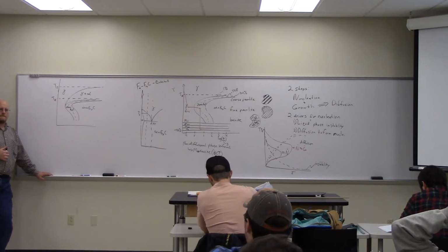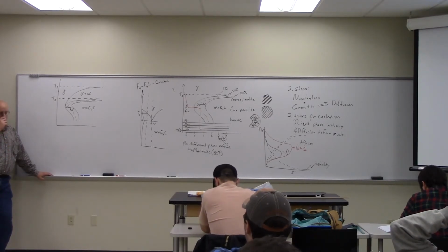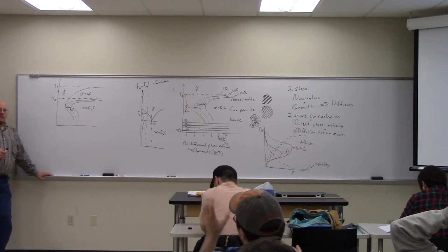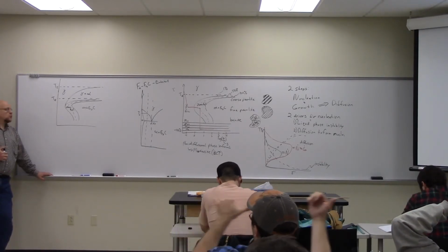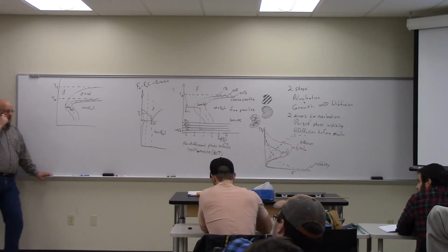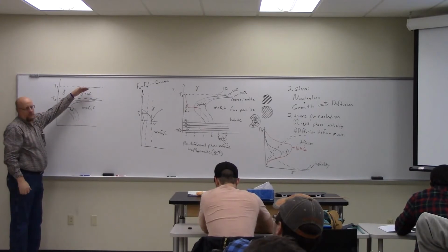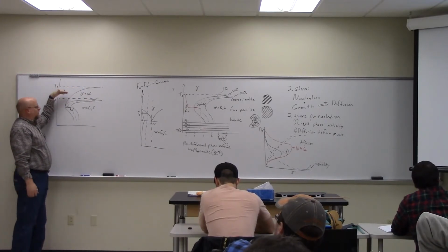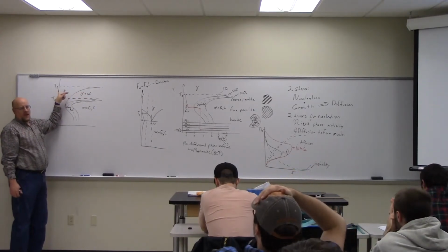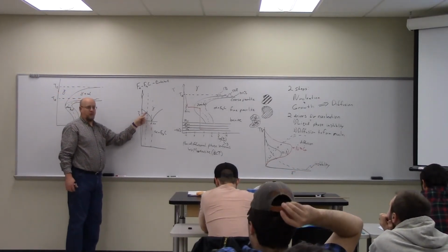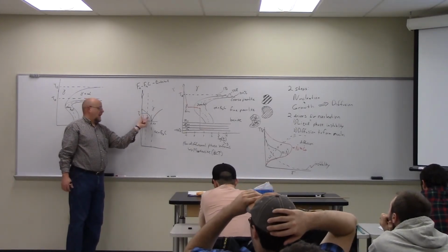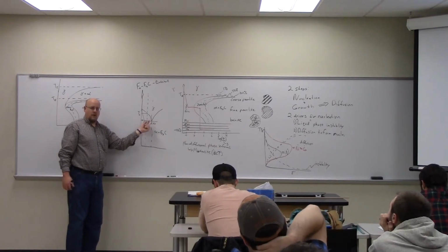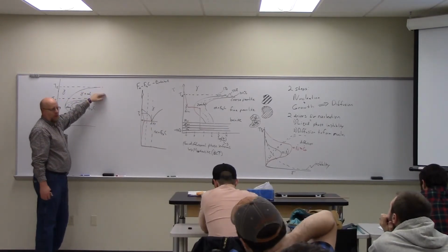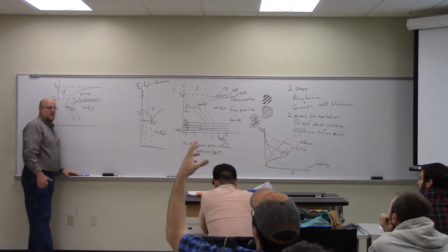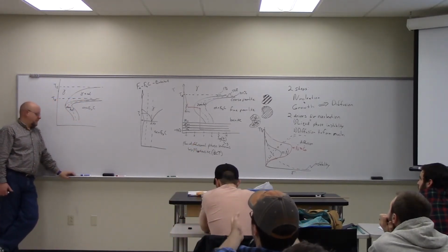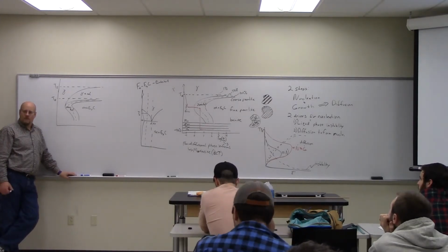That makes sense to everybody? And as we go into that gamma plus alpha section, it would be a different concentration of gamma plus alpha, getting more and more alpha as we go that way. No, the amount of alpha is, this is just a percent transformation. And generally we only draw the top, where you start the transformation. So as I go across here to the right, I'm converting more of my gamma to alpha, but I'm never going to get any more alpha than I'm supposed to have in my system, right? It's the inverse lever rule that tells me how much alpha. So the amount of alpha will never be more than what it's supposed to be. Yeah, but the farther you go this way, the more complete that alpha reaction will be, but it will never exceed the amount it's supposed to. Okay, any questions?